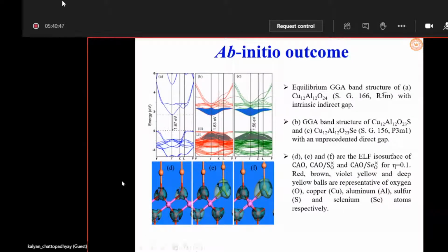I just spent 2 minutes here because the results are very interesting and important, I think. You see, the leftmost panel, this one, is the band structure of pristine copper aluminum oxide. And look at the number of features. First of all, you see the valence band maxima is not at the same k value as the conduction band minima, that is the gamma point. So you have an indirect band gap. This is the first thing.